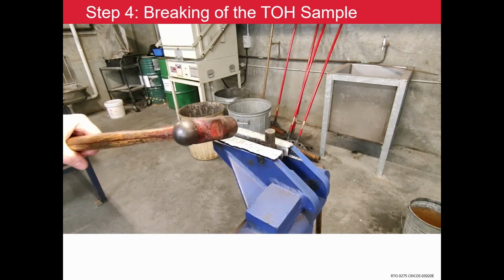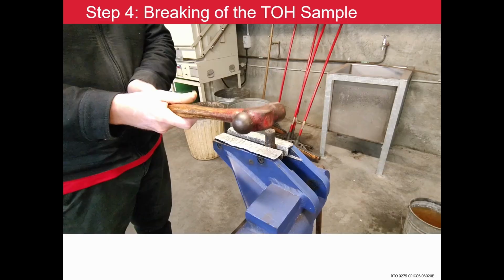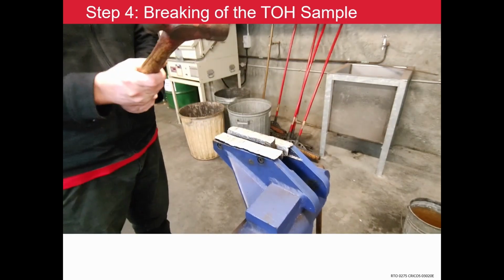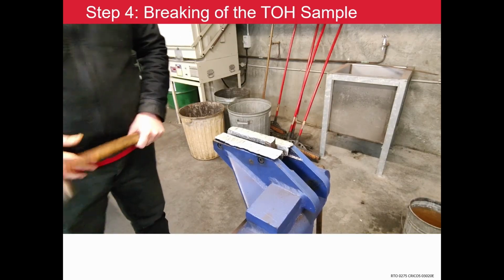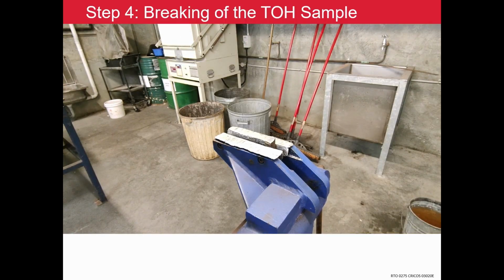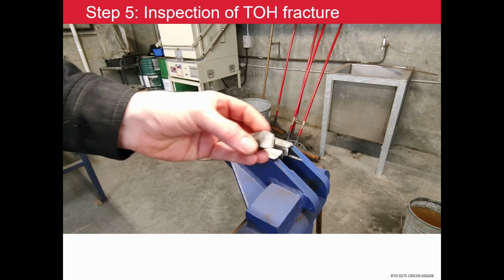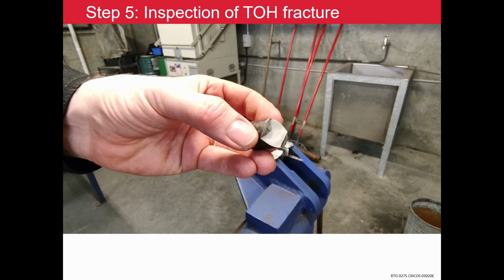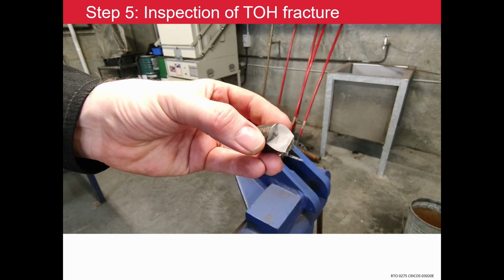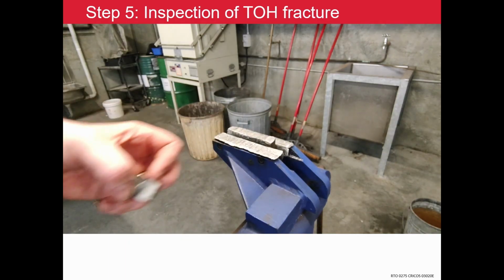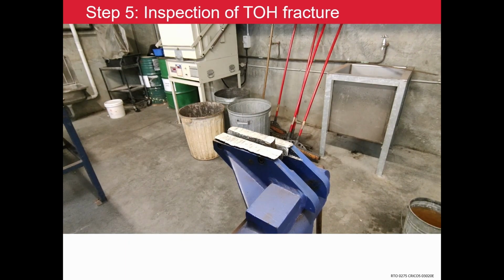The TOH sample is placed in a vise and struck with a hammer. The sample fractures in a brittle manner due to its martensitic structure and the stress concentrator notch that was cut into the sample previously. The fracture surface is inspected. It shows a granular, crystalline appearance typical of a brittle fracture, with no evidence of plastic deformation. The grain structure can also be observed.